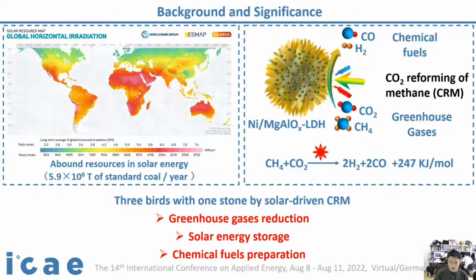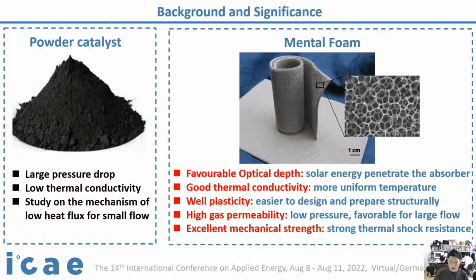We call it three birds with one stone because the greenhouse gases reduction, solar energy storage, and chemical fuels preparation could be achieved by solar-driven CRM at the same time. Unlike the large pressure drop and the low thermal conductivity of powder catalyst, metal foam is chosen as the catalyst support due to its favorable optical depth, good thermal conductivity, good plasticity, high gas permeability, and excellent mechanical strength.